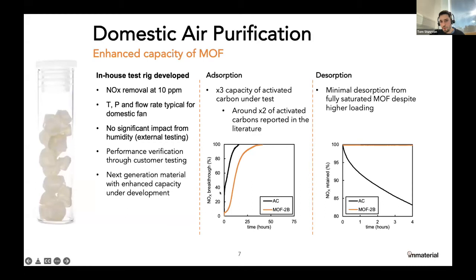And just to explain what you're seeing on these graphs, so if I go to this graph in the middle, this is introducing that NO2 stream, and the percentage that you're breaking through is where this line's plotted. So when this line reaches the top, that means all 10 ppm is breaking through the filter bed. And the two plots here, the AC, that's standing for activated carbon. So we extracted activated carbon from a commercial filter unit and compared our MOF2 to that activated carbon. So you can see a similar sort of shape profile to our MOF2, but really what we've got is around 3 times the capacity of the activated carbon that we extracted. So the total area above these curves gives you an idea of the total amount of NO2 that's absorbed.